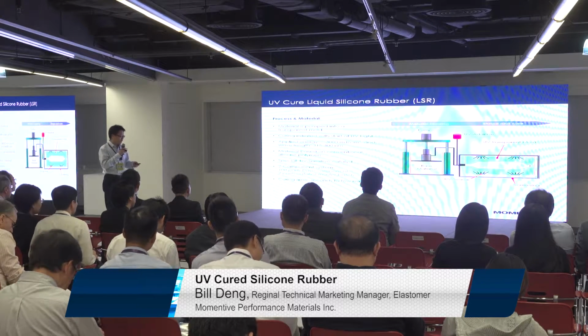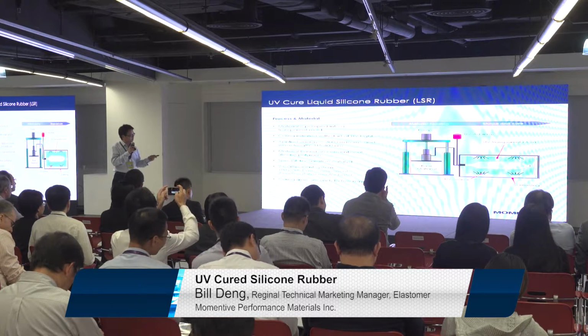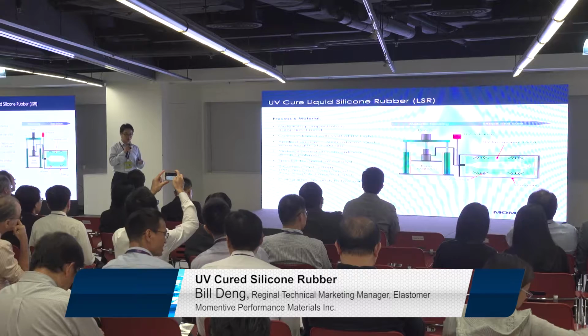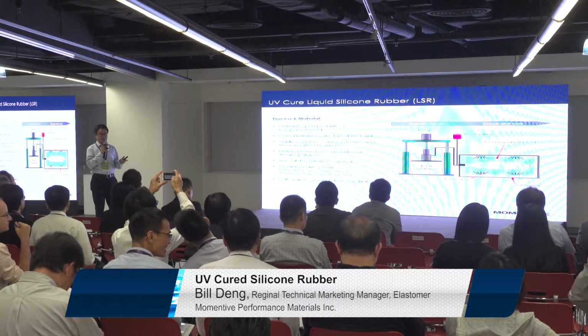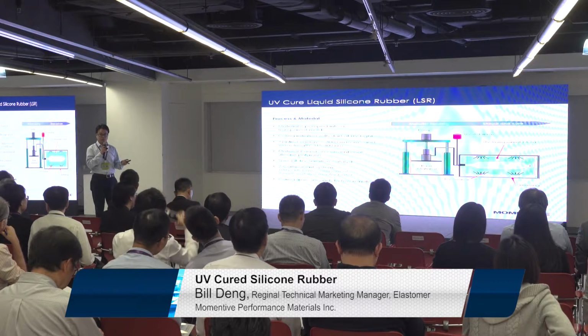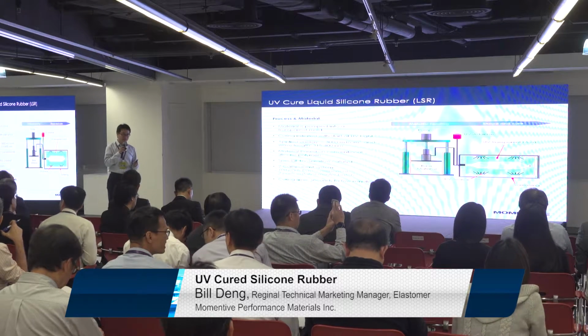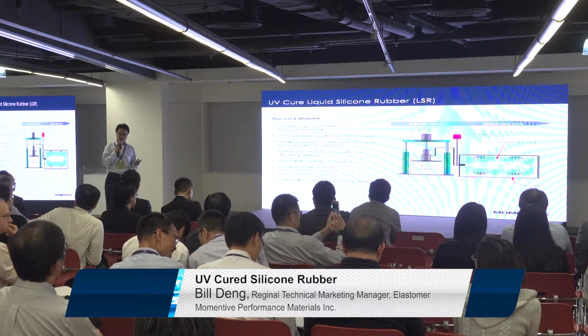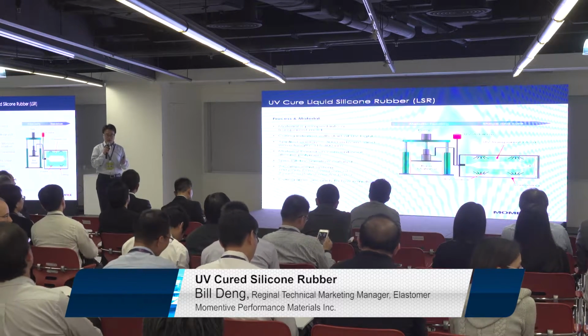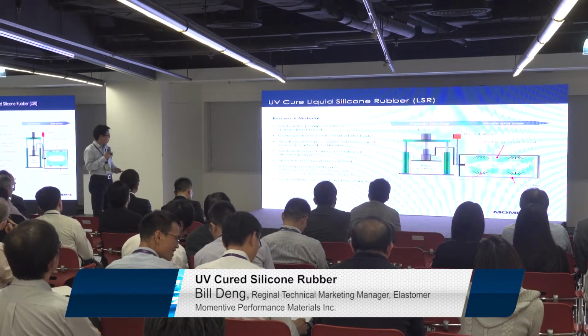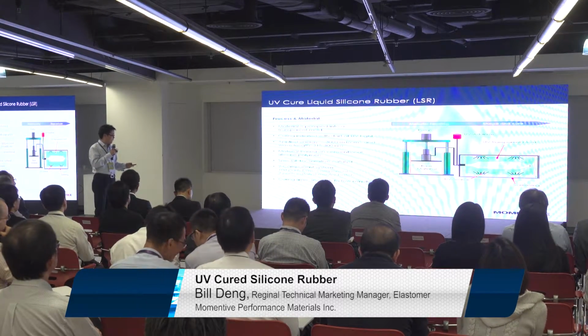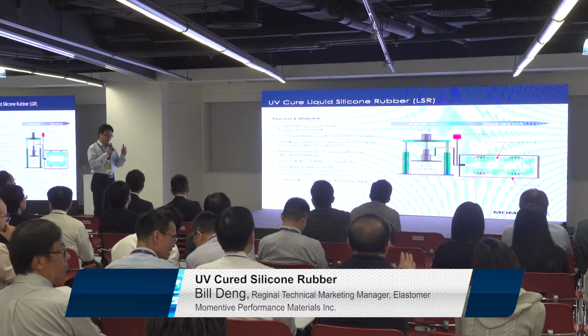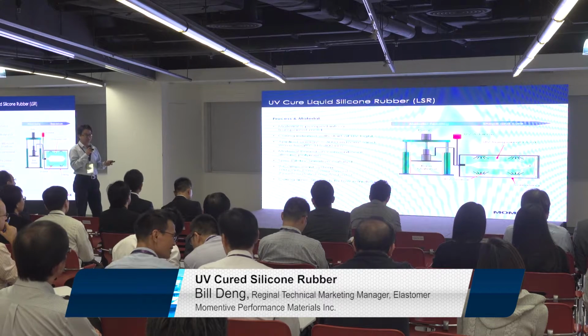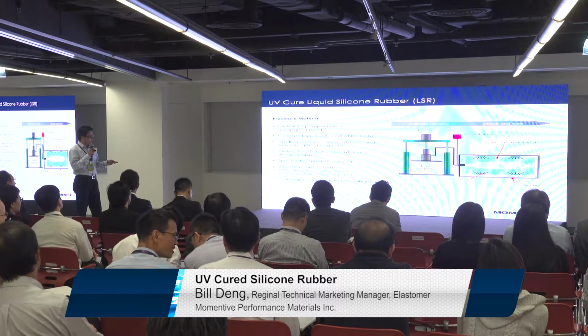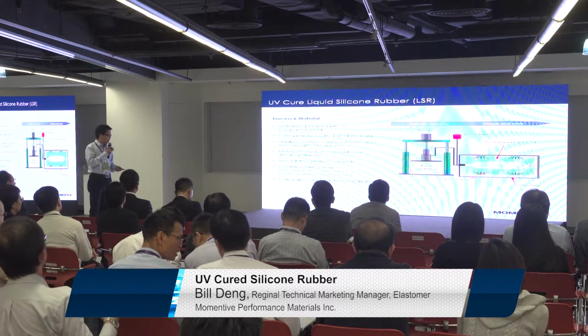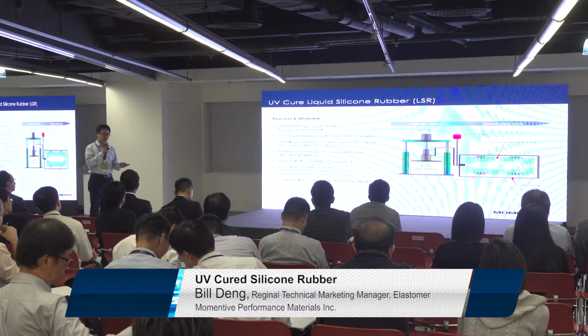And of course, from Momentive, if you want to get UV LSR material, we have a pail kit and a drum kit. For the pail kit, usually 15 kg of B as the base material with 2% A catalyst. For the drum kit, we have a 200 kg drum as the base material with 2% catalyst. And because UV light is very fast, faster than other media, the curing time is very fast as well. Usually we only need a second to a few minutes. You can make a big part.